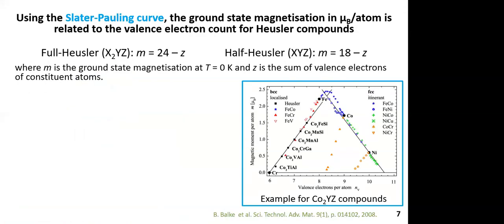So here I am showing an example for cobalt-based compounds and how they follow the Slater-Pauling law. So we can see that the ground state magnetization, which is given in magnetic moment per atom, in mu B on the y-axis, is related to the valence electron count. So for full Heusler materials, which have the form X2YZ, the magnetization m is equal to 24 minus z, where z is the sum of the valence electrons of the constituent atoms. For half Heusler materials, which have the formula XYZ, we have m is equal to 18 minus z.